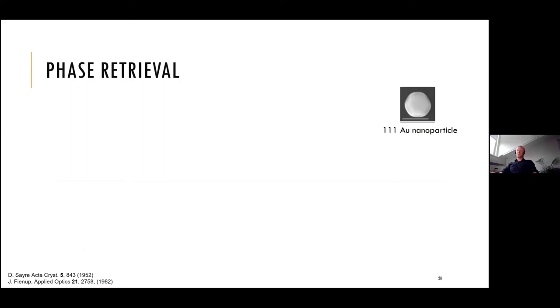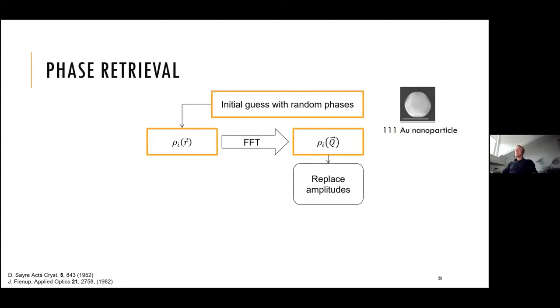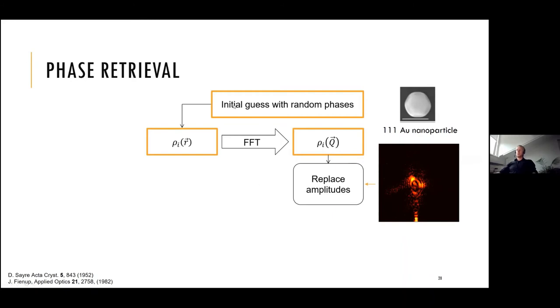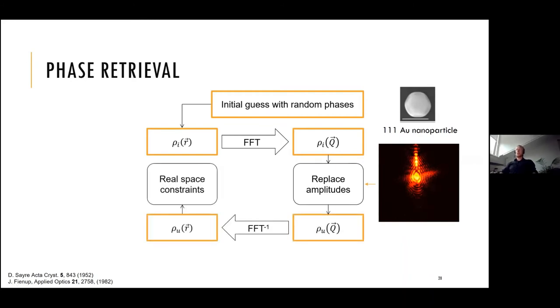Let's look at an example of the gold standard of Bragg CDI, which is basically a gold nanoparticle which scatters a lot and has a nice shape. And you measure normally the 1-1-1 reflection, which is normal to the surface. You use some initial guess with random phases, and then you go through this iterative process, substituting the scattering amplitudes, which look like that in reciprocal space, and real-space constraints, which are the shape or positivity and so on.